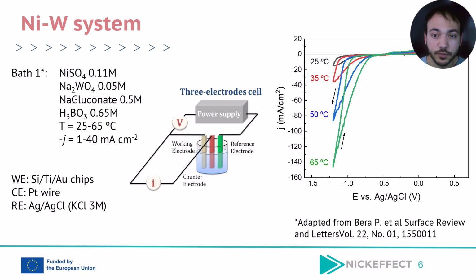For the deposition of the films, we used the following gluconate-based bath. A standard 3-electrode cell was used to deposit the samples using silicon chips with sputtered titanium gold layers as a working electrode. As a counter electrode, we used the platinum wire, and the reference was silver chloride. Here you can also see the cyclic voltammetries of the bath at several temperatures.